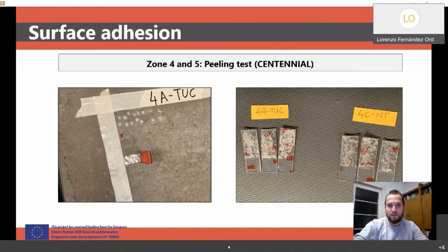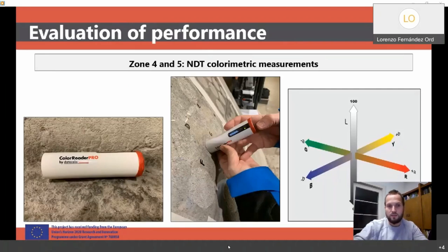Here you can see also the surface adhesion tests, where you can see some of material which appeared on the blisters during the first interval of the measurements. But after two more months, much less of product was taken during the peeling tests. So maybe it needed more time to go through the structure of concrete. And we checked also the colorimetric properties of concrete after application of product.